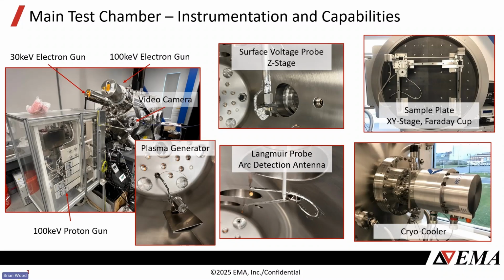We have other measurement probes, and so we have the Langmuir probe to characterize our plasma when using the plasma generator. We have a Faraday cup that's always mounted on the sample side to monitor the flux of the electron guns or the proton source. We do have a surface voltage probe, which is a non-contacting electrostatic probe. So you can charge up your instrument or your material, and then we can sweep that across the sample to measure what surface potential it's reached due to some incoming radiation. And that's located on a Z stage that allows us to sweep it up and down across the sample.